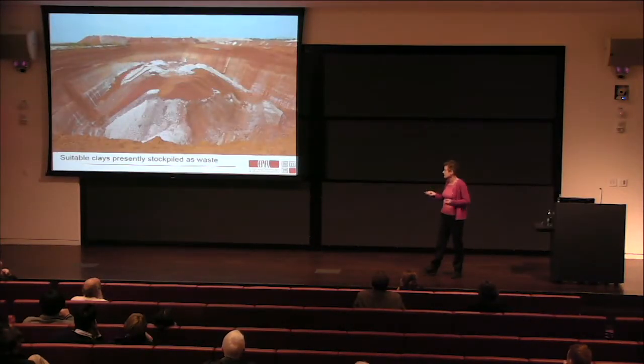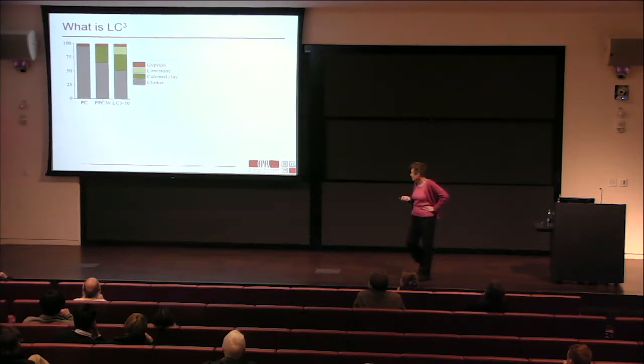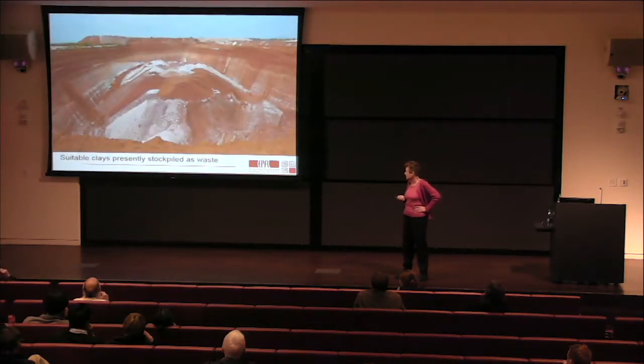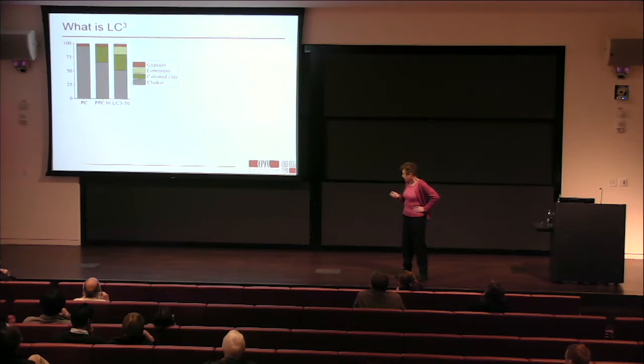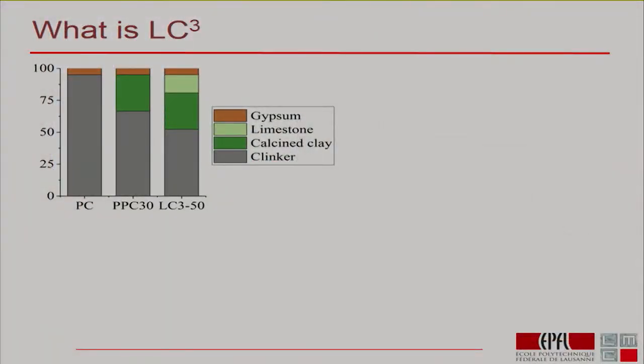It's a waste in the same way that slag and fly ash are waste. Now, here's what is really the secret: this is a Portland cement, which is clinker and gypsum. We've for a long time known about these kinds of pozzolanic materials, where we typically have 70% clinker and about 30% pozzolan. It can be calcined clay, can be fly ash, can be whatever.